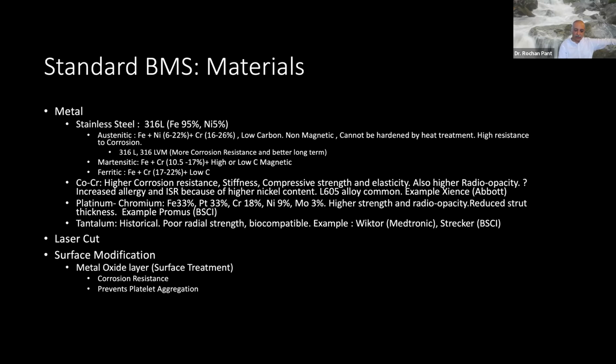Tantalum has been used for stents earlier, but right now it's of historical interest only. There's hardly any tantalum stents available in the market today. So the other part is that all these materials undergo surface modification, because if you keep a pure metal surface, that tends to get oxidized and corroded faster. So actually all these stents have a layer of metal oxide on them, for example, like aluminum vessels have, which protects the aluminum from reacting with the environment.